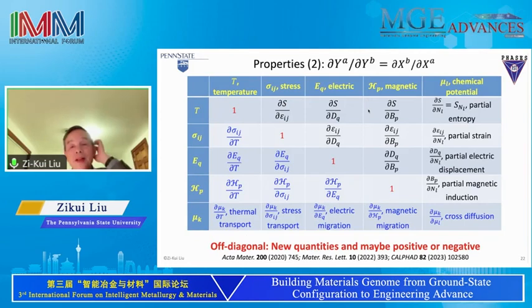And it's more important that in this set of derivatives between two potentials, for example, between the chemical potential and temperature derivative, that's thermal transport. That's the Soret effect. If this is electron, that's the thermoelectric effect. Okay. So that means this Seebeck coefficient is also a second derivative of energy. Again, this is because the off-diagonal terms can be either positive or negative. The question is how to predict it, right? As I mentioned, if we can calculate the free energy, we can predict it. That's exactly what we did for negative thermal expansion in our work published in the last several years.